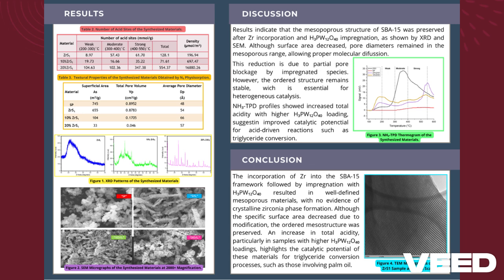Discussion. Results indicate that the mesoporous structure of SBA-15 was preserved after zirconium incorporation and phosphotungstic acid impregnation, as shown by XRD and SEM. Although surface area decreased, pore diameters remained in the mesoporous range, allowing proper molecular diffusion. This reduction is due to partial pore blockage by impregnated species. However, the ordered structure remains stable, which is essential for heterogeneous catalysis. TPD of ammonia profiles showed increased total acidity with higher heteropolyacid loading, suggesting improved catalytic potential for acid-driven reactions such as triglyceride conversion. Maintaining an ordered mesostructure while significantly increasing acidity is challenging in heterogeneous catalysis. These results indicate that our catalyst is both structurally stable and chemically optimized for industrially relevant processes, such as biodiesel or green diesel production from palm oil.